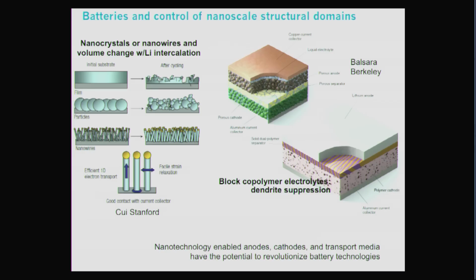Is that important? Yes, it shows up directly in energy technology. This is a scaling law now that says small crystals can be quite perfect in their structural transformations. They can alter shape. They can withstand chemical transformation with enormous volume changes. Well, it turns out that shows up very directly in energy storage. In energy storage, we would like to take lithium and put it into a new domain, and the volume has to change. It might change by as much as 20 or 30% when the lithium is incorporated.